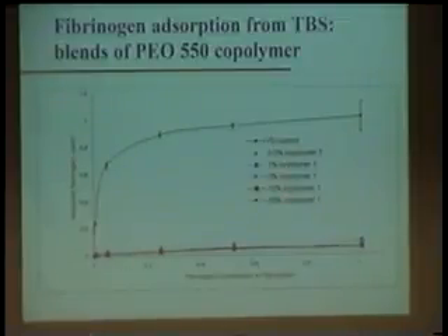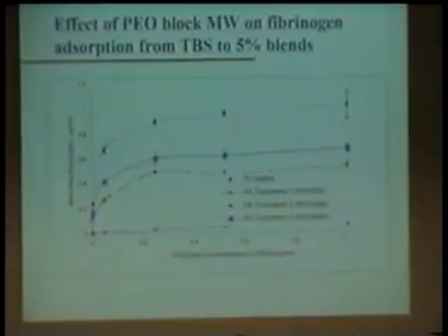And as you blend in more and more of the copolymer, you can't see it too well in this because of the scale, but it goes down a little bit. So this is a pretty convincing, for me at least, demonstration of the effectiveness of this approach to using PEO to obtain a non-fouling surface. Show you some more data on that.